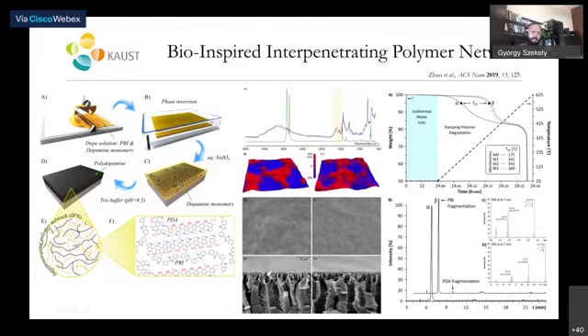So the technique is to blend together in a dope solution your original membrane material, in this case PBI, and blend in the monomers of dopamine. Then we do the phase inversion, where the membrane actually forms in water. The next step, or two steps, is to initiate the polymerization of the dopamine monomer. These are the monomers that are randomly distributed inside the membrane, and during the polymerization, you get polydopamine that covers the membrane.